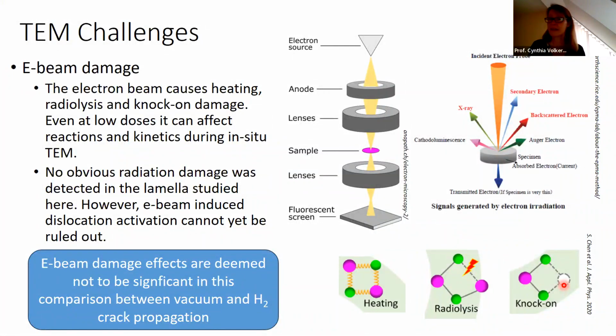We have materials, and you'll see one a little bit later, namely wood, where the damage from the electron microscope is very significant, and we see that right away and must find methods to avoid it. But for the study of the steel, there appears not to be significant effects of electron beam damage. So that's an important challenge for the TEM that always needs to be considered. In this particular case, we believe that it's not the main effect of what we're observing in our materials.